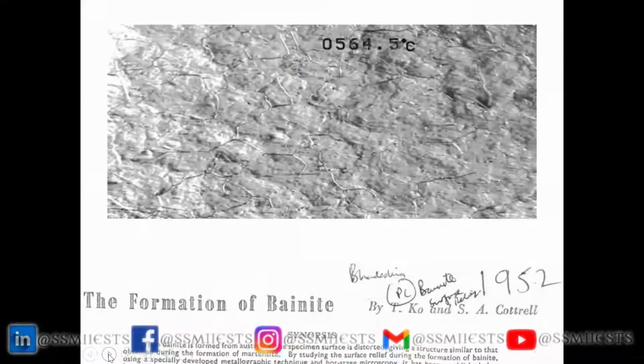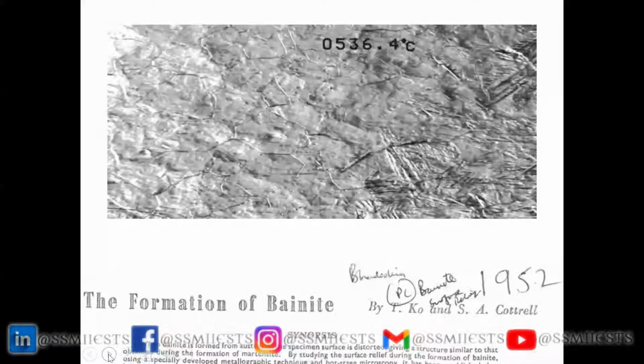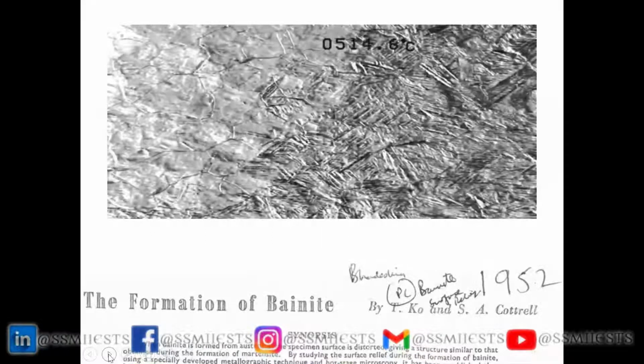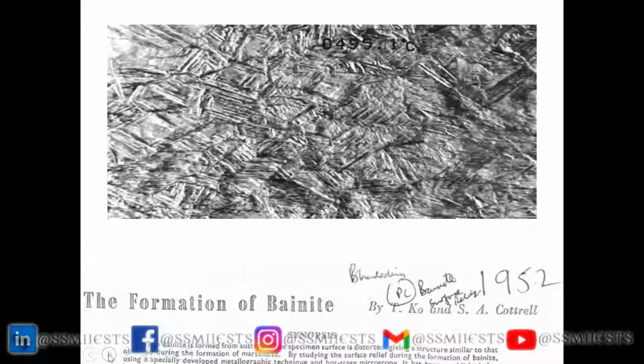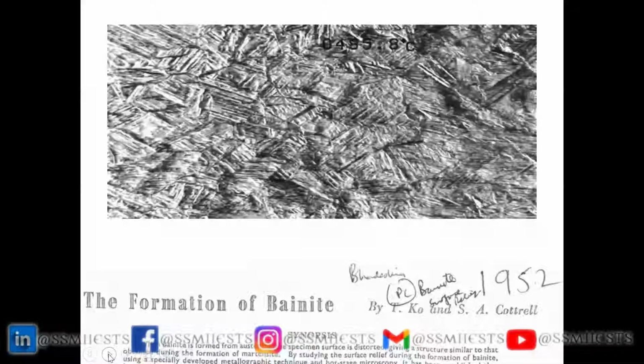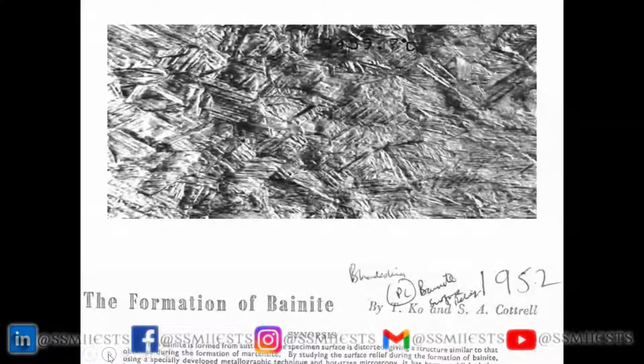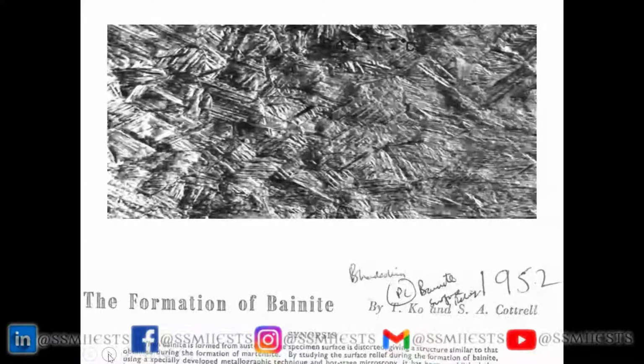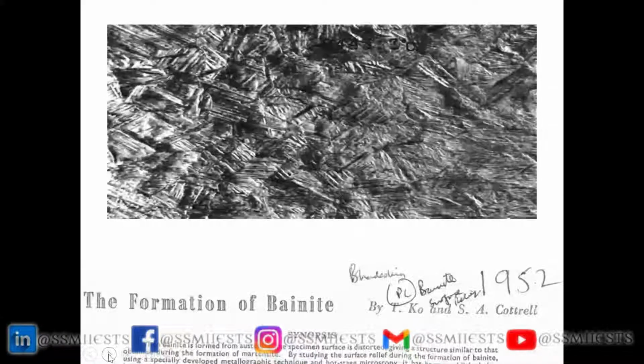If I take a sample of austenite and I polish it completely flat, and then I allow it to transform into bainite, then you can see that it produces quite severe deformations, right? And these deformations have a special characteristic that they involve a very large shear deformation. And in order to minimize the strain energy associated with the shear deformation, the bainite plates form as very thin plates compared with martensite, for example. So martensite plates will generally grow all across an austenite grain, and therefore they tend to be coarser. So these plates are only 1/4 of a micrometer in thickness.